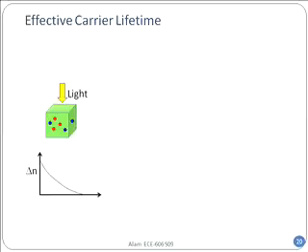So when you shine light and then turn it off, it's going to go down. From experiment, I'm saying, if you look at the output light that is coming out, you will see it is decaying as a function of time. The x-axis is time, the y-axis is delta n. And t equals 0 in this one is when I have turned the light off. I'm just looking at how the photons are coming out. So from experiment, what I will get is something called a tau effective. That's how I'll see the whole thing decaying.